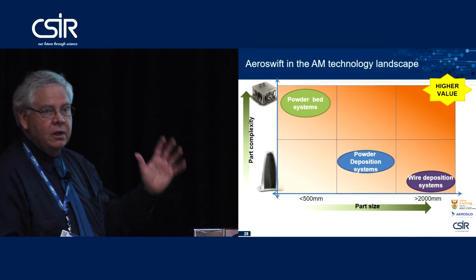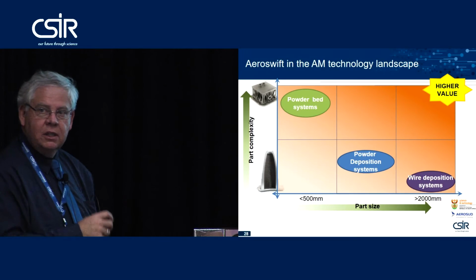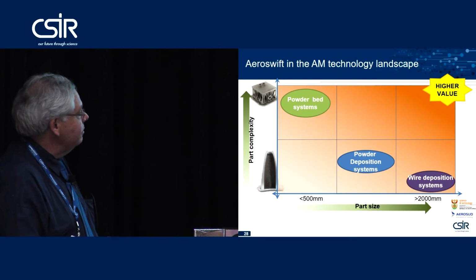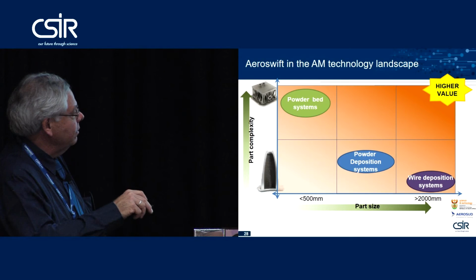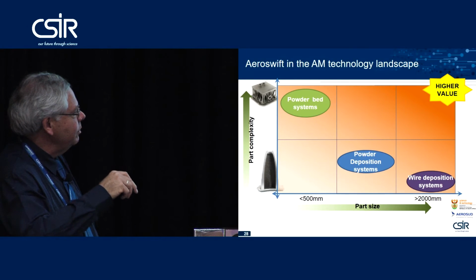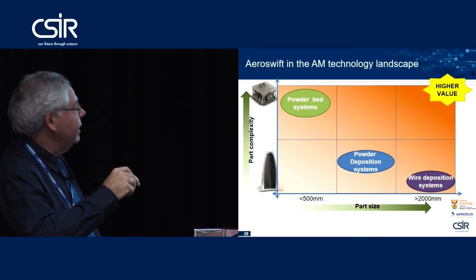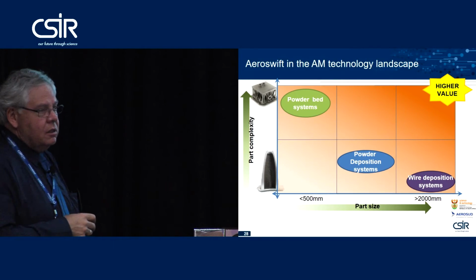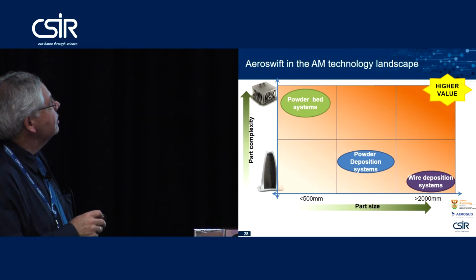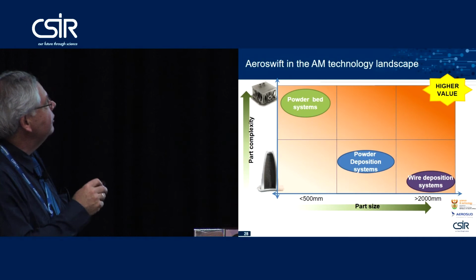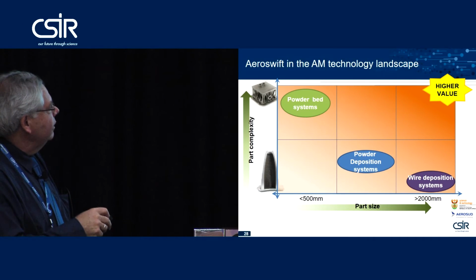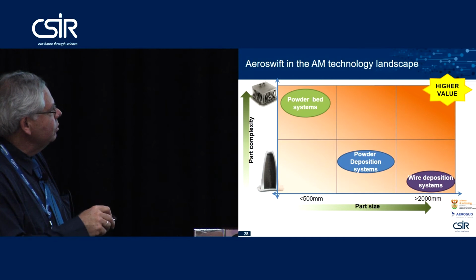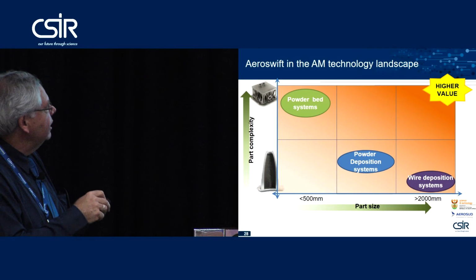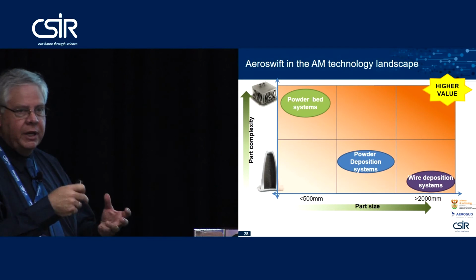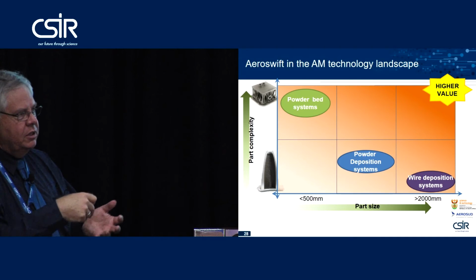So this is a very simple graph, but it just demonstrates where Aeroswift fits into this competitive landscape. If we have the capabilities plotted in terms of part size on this axis versus the complexity of the part on that axis, present commercial powder bed systems basically make small parts but very highly complex parts. And if we think about laser metal deposition, the one that I've just showed you, we have larger parts possible but less complex parts, because we basically spray the powder into the laser beam and the robotic system determines the resolution.